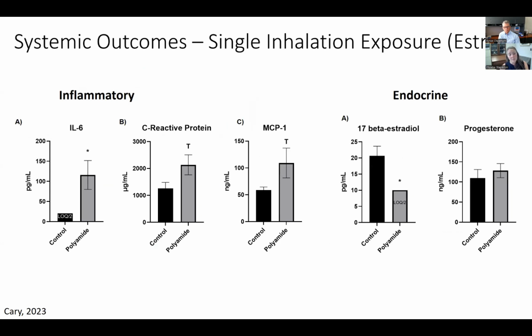Further, we did see some systemic inflammation. So this was in the plasma of these animals, again, 24 hours after exposure. We saw an increase in IL-6. We saw an increase that didn't meet full statistical criteria, but it was less than P 0.1, but not less than P 0.05. But we did see increases in IL-6, C-reactive protein, and MCP1.